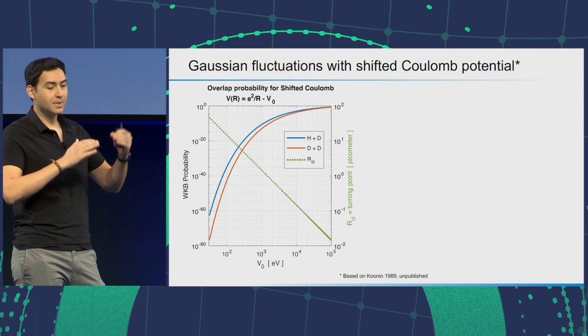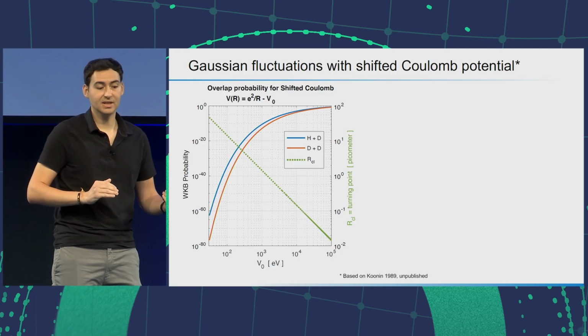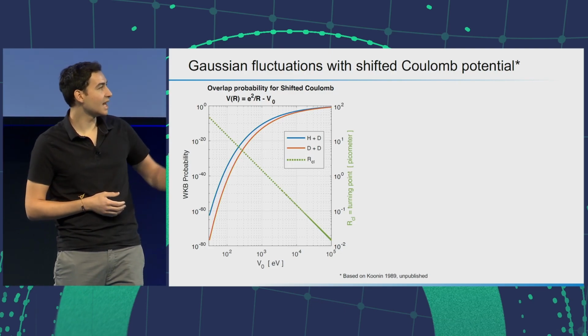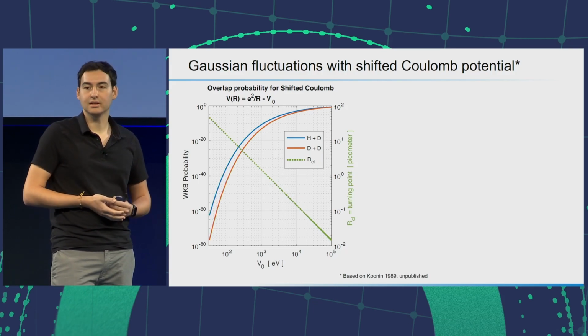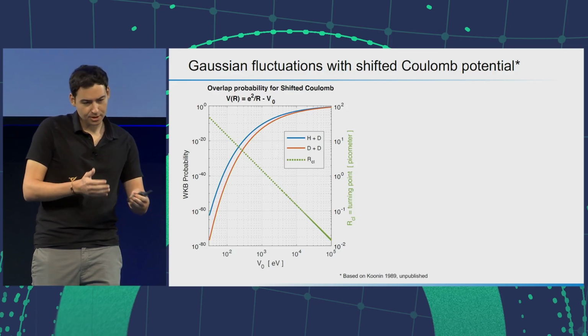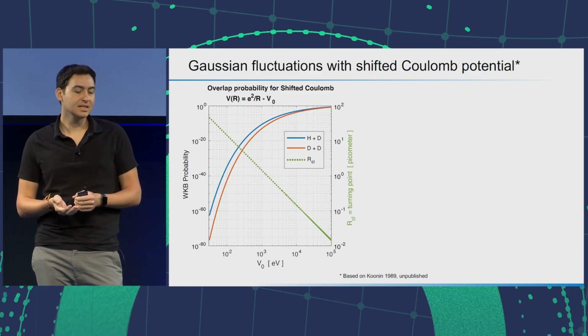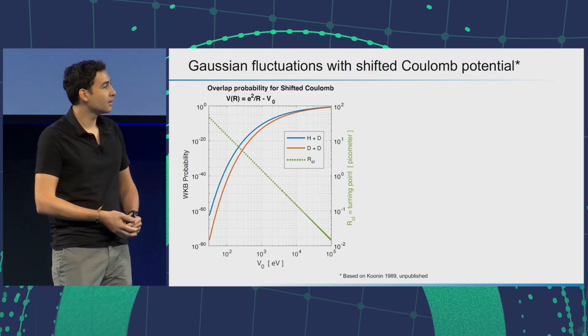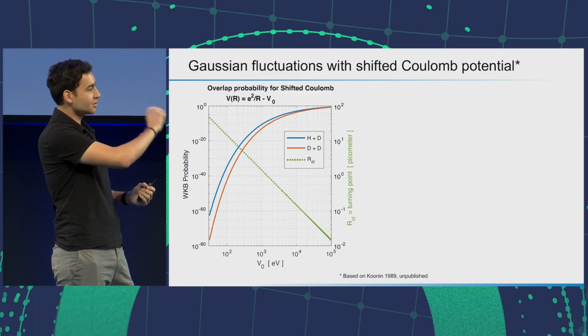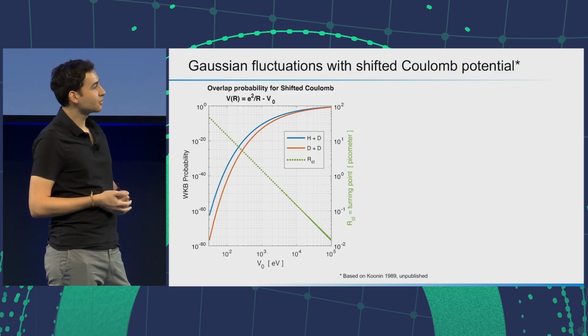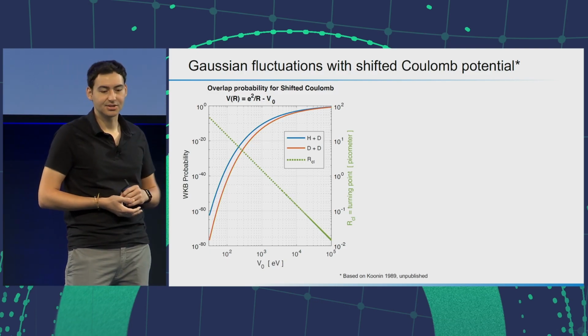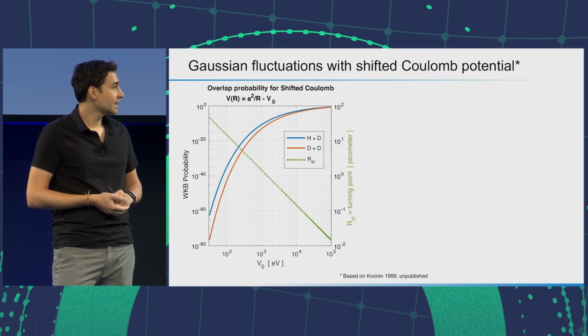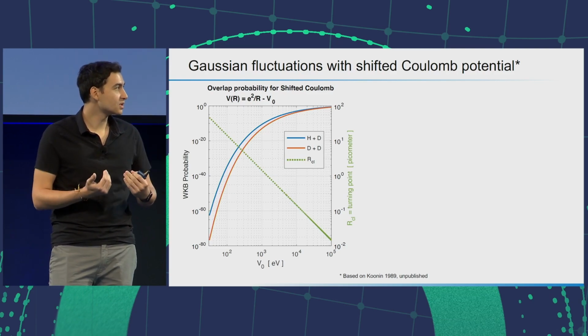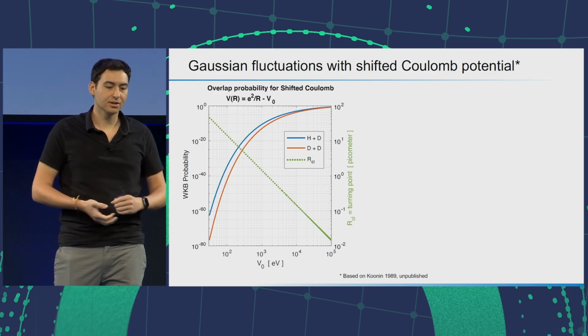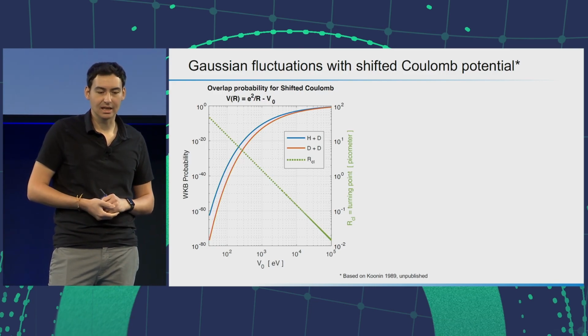You could shift your bare Coulomb potential by a screening energy V naught, and that's plotted on the horizontal axis. And on the vertical axis is the tunneling probability. And so here we're looking at different reduced mass, so H plus D or D plus D, as a function of this screening energy. And as you can see, you turn the knob, increase the screening energy, and the tunneling probability takes off. In green is the classical separation distance. So as you reduce this barrier, it's much easier to get a classical turning point that's a lot smaller.